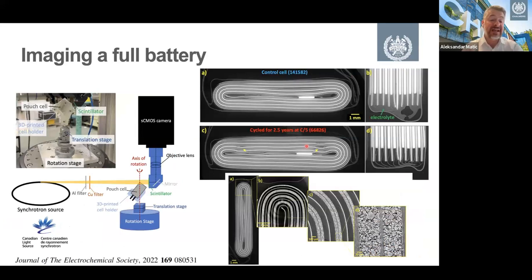Here's another beautiful example from the Canadian Light Source. Here they put in what is called a pouch cell. So this looks like a small coffee bag, which contains layers of your electrodes you see here in this kind of geometry. So here they actually took a control cell, a pristine one, and then they looked at a cell cycled for 2.5 years. So quite extensive cycling. And you see here you have the nice homogeneous layers, whereas here you can see that we have some problems with delamination, with some cracking. In this case, they could actually zoom in, you see, from the full pouch cell towards a part of the layers, and even down to analyzing individual grains. So really providing this capability to cover large length scales.